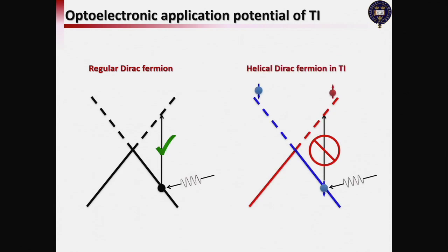But in the helical Dirac surface state in the topological insulator, although the dispersion looks similar, there's a fundamental difference, because these two state bands have opposite spin. So if you try to excite the downspin to the upspin channel here, it's pretty hard, if not impossible. Right? Well, there's spin orbit coupling. There will be a small chance to jump up, but it's greatly suppressed. So we tried making use of this idea.